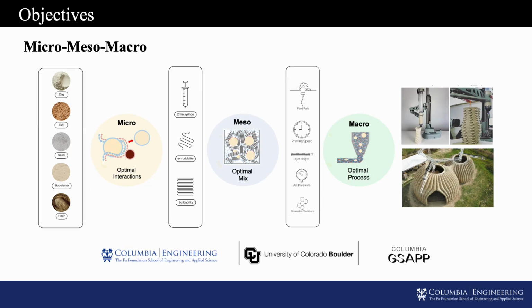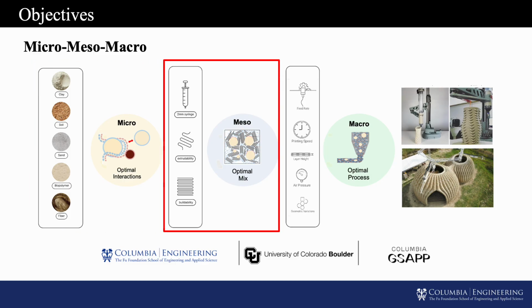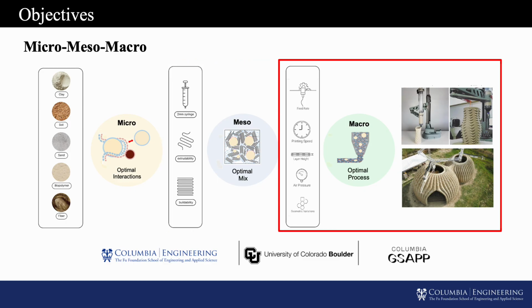For this purpose, we applied a 3M method. First, we investigated the micro-level particle interaction between clay minerals and biopolymers, or biopolymers and sand, then studied how these micro-level particle interactions affect meso-level rheology and small-scale 3D printing. Eventually, our architecture lab will help us to scale up these results to macro-level, large-scale printing.